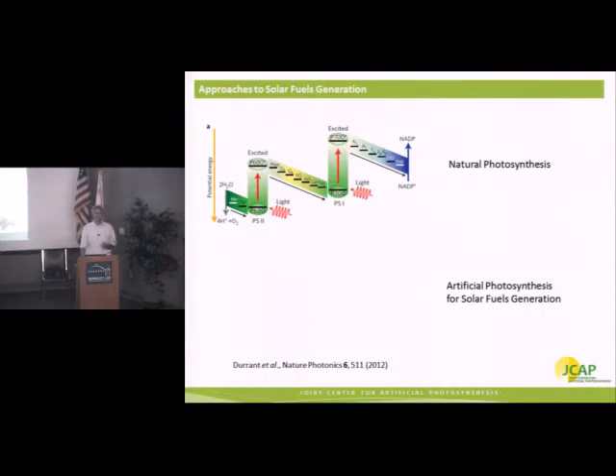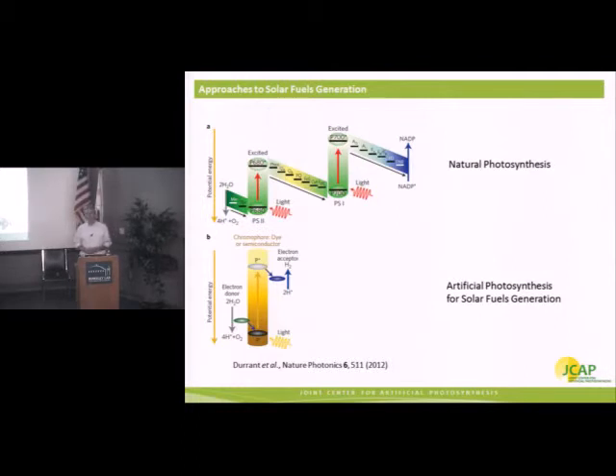Once a photon is captured, charge separation and conversion happens with a very high degree of efficiency. And so we would like to take inspiration from this and mimic that process. And we are doing this with inorganic semiconductors as the light absorbers in this case. So there are a few approaches to this. One of them is based on using a single semiconductor. On one side of it, you can put a catalyst for water oxidation. And on the other side, you can put a catalyst for hydrogen evolution.